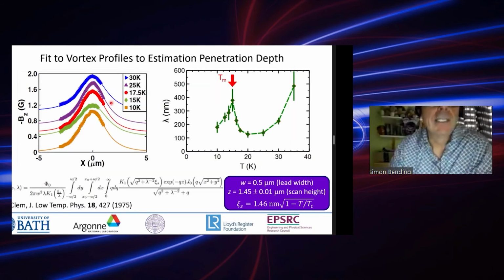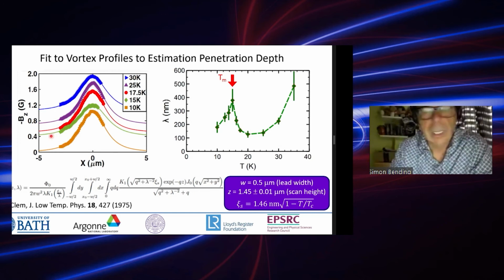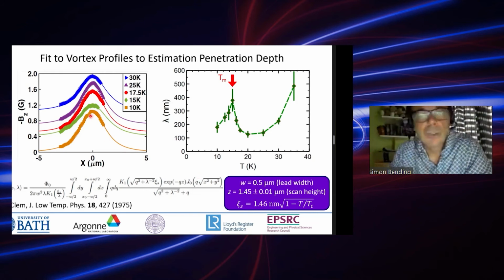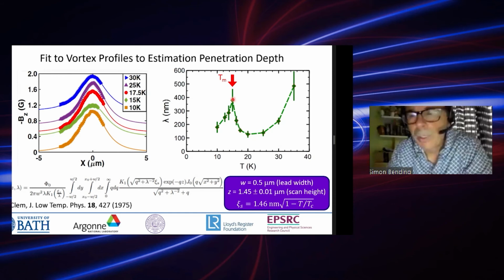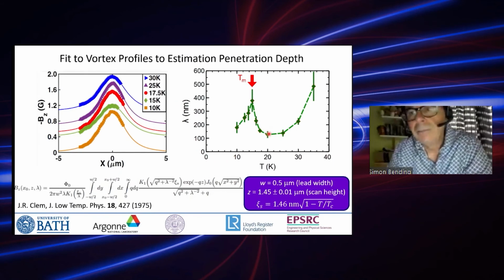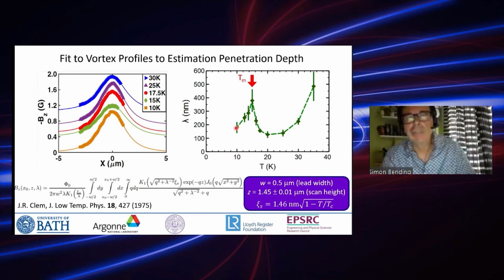And it's the error bars, in fact, on this scan height that set the error bars on the data that I'm showing here. So you can see from these fits, the solid symbols of the data and the continuous lines of the fits, that we can fit our data extremely well with one consistent set of parameters as described by this panel here. And that allows us to extract the penetration depth lambda as a function of temperature, which I've plotted in this plot here. And you can see as we reduce the temperature from 30 Kelvin, initially the penetration depth shrinks. As we approach the magnetic ordering temperature and the fluctuations kick in, we see a very pronounced broadening of the penetration depth, almost a factor between 3 and 4. And as we cool down still further into the more ordered helical state, we see then that the penetration depth recovers, if you like, and shrinks again.